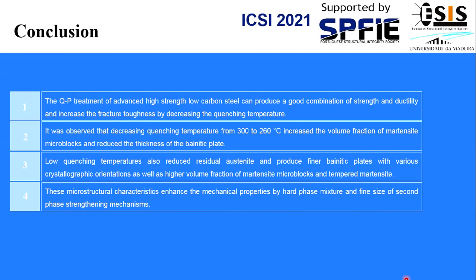Conclusion: the quench partitioning treatment of advanced high-strength low carbon steel can produce a good combination of strength and ductility and improve the fracture toughness by decreasing the quenching temperature. It was observed that decreasing the quenching temperature from 300 to 260 degrees Celsius increased the volume fraction of martensite and reduced the thickness of bainitic plates.